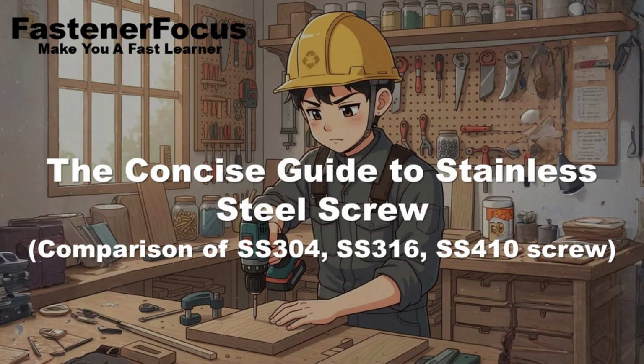Ah, so the acid essentially cleans the slate. It dissolves only those contaminants and leaves the pure chromium-rich alloy behind. Exactly. The acid dissolves those contaminants along with any low protective oxide scales that might have formed during heat treatment. Once the fastener is rinsed and dried, this freshly clean, uniform chromium-rich surface spontaneously reforms an optimized passive layer upon immediate exposure to oxygen. And this professional treatment results in a measurable performance increase.